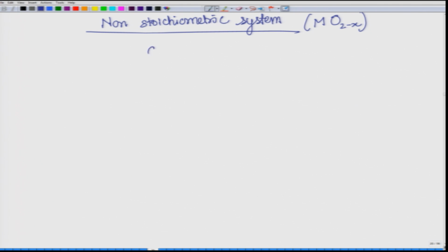So, some part of the oxygen has left the system and gone into the atmosphere. How do we represent this? Basically, oxygen at its oxygen site, which has neutral charge, forms a vacancy at the oxygen site, and let us assume that it leaves in a neutral state, meaning the charges remain with the site where it was, because we have to maintain charge neutrality.